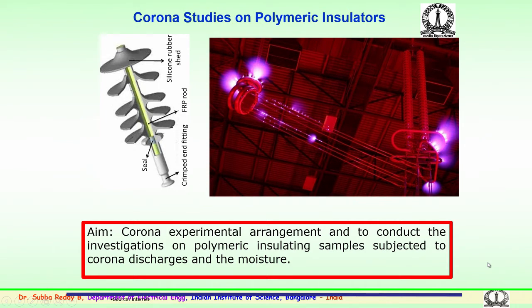Various types of samples are to be subjected to corona discharges during normal conditions, that is dry conditions, and also to see the performance during moisture. Moisture means light rain, drizzle or fog. This aggravates the corona activity, where the combination of corona with moisture would further degrade the surface of the polymer. This has to be studied in detail, as very little information is available in the literature since these insulators are of recent origin. So, studies have to be carried out on this aspect.